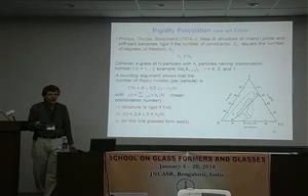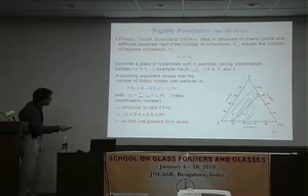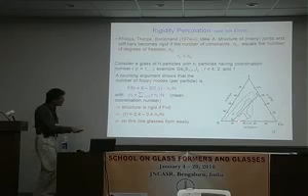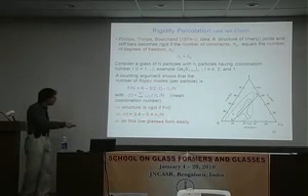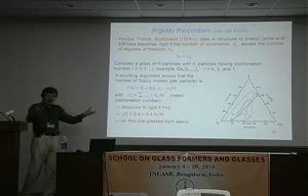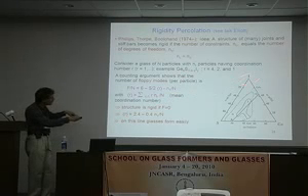Silvio, you were starting to comment on the line and then you were interrupted. Can you comment on the line? Sure, sorry. So the line is the prediction of this. Okay? So they predict that this structure is ideally rigid. It's not over-constrained, it's not under-constrained. On this line here, if you put in the right numbers, how the R depends on the concentration of the sulfur and the germanium, you get out this thing.